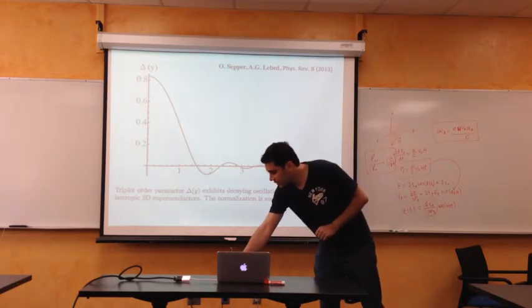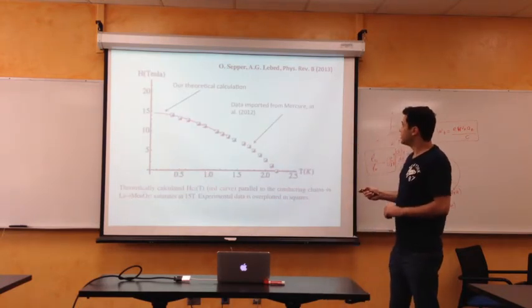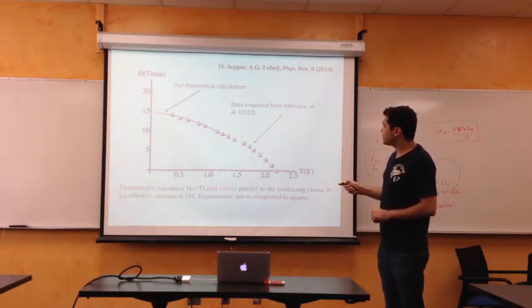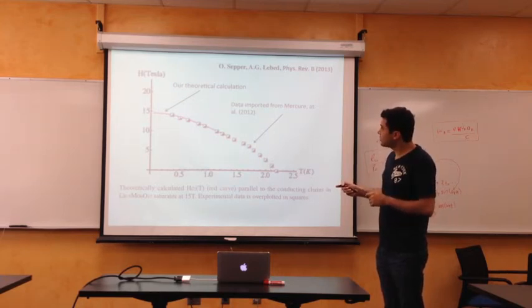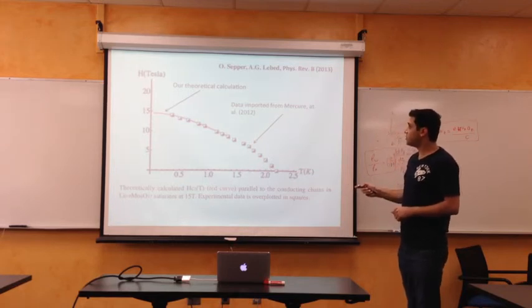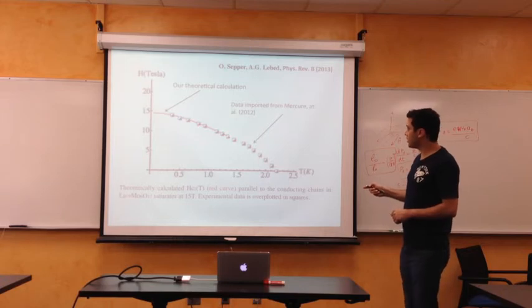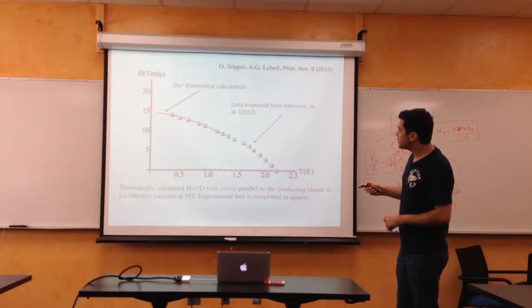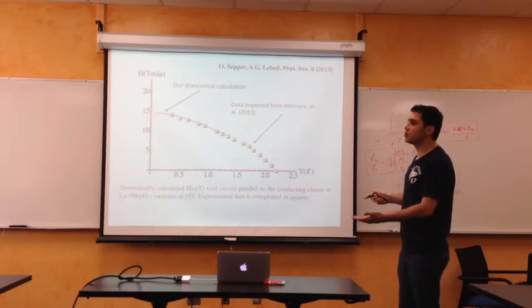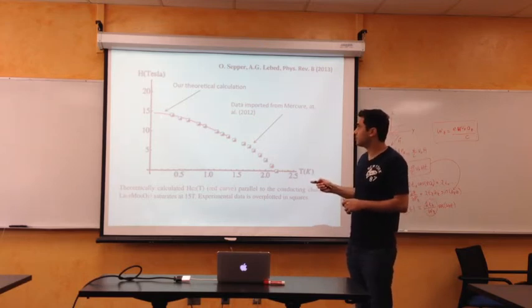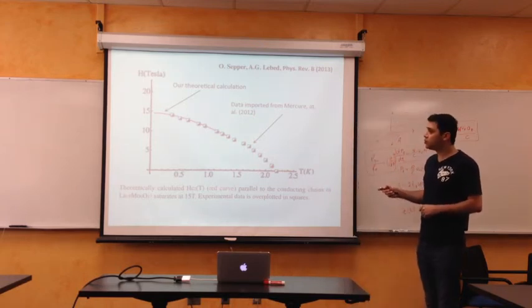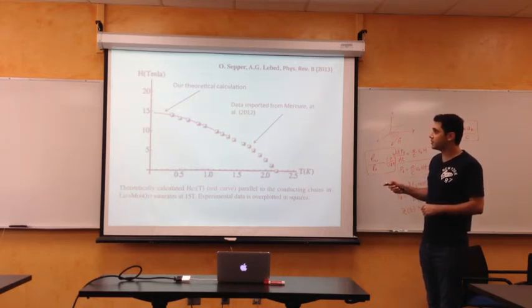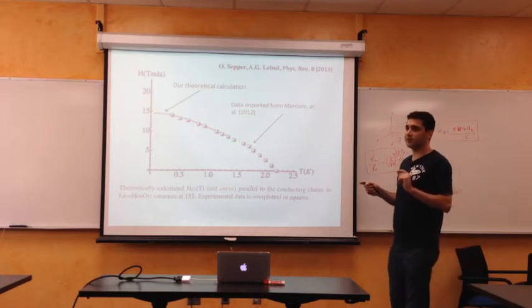And we calculate the magnetic field. So, this is our important result. The red curve is our theoretical calculation. It shows that indeed for a parallel magnetic field, superconductivity is destroyed at around 15 Tesla, and it fits experimental data pretty well. We went until up to about 1.5 Kelvin for our calculation, and down to about 0.06 Kelvin, after which quantum effects become important, but you can extrapolate the saturation point to be about 15 Tesla. So good quantitative agreement with experimental data, and we didn't use any kind of parameter fitting here.